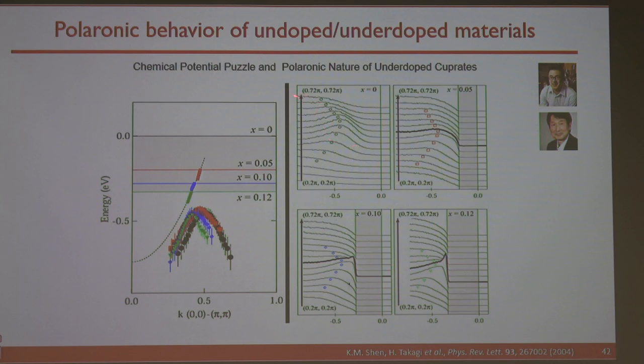Remember I said the total dispersion is described by magnetic interaction, but you cannot describe its tremendous width, especially the width at the top of the feature, you can see here. This width looks like a Gaussian. Okay, so you need something else to further broaden it, and that he termed the polaronic phenomenon. By resolving that, we will also explain the long-term question about what happened to the chemical potential when you dope the system. Okay. This was pointed out by Jim Allen that there's an inconsistency between the doping you have and the expected chemical potential shift. Okay. So we were able to do that.